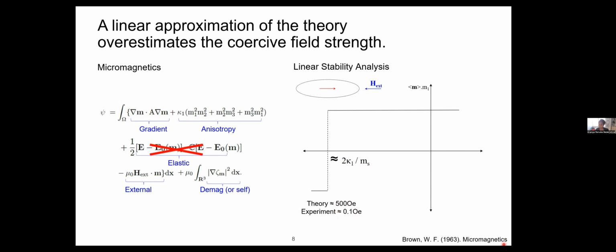And so in his book, he described this as the coercivity paradox, which essentially means that doing a linear approximation of this well-established theory is not predicting the coercivity or the hysteresis width of these materials well. So there must be something that's missing.